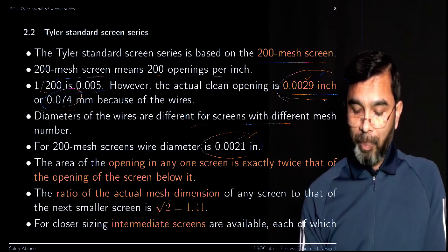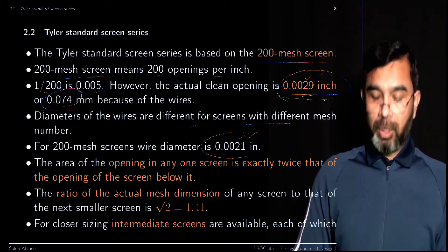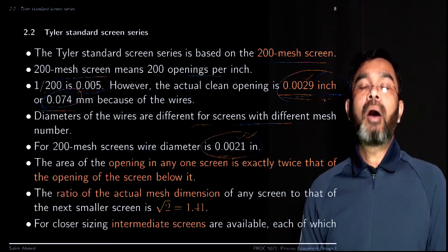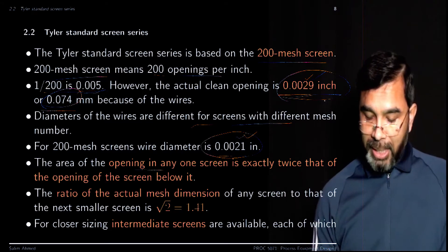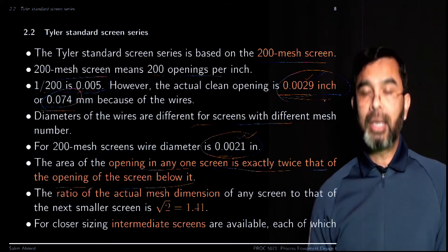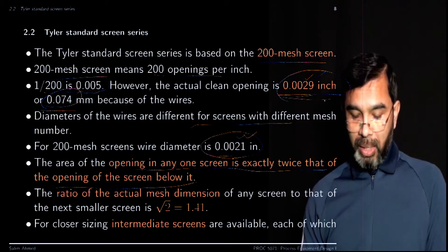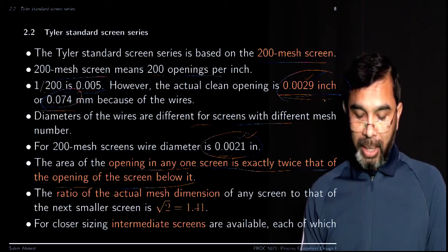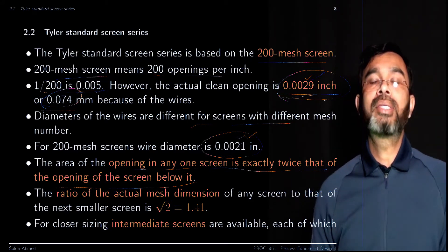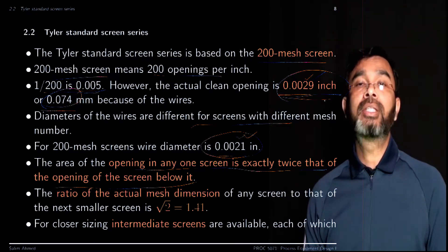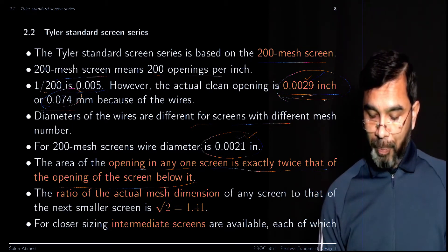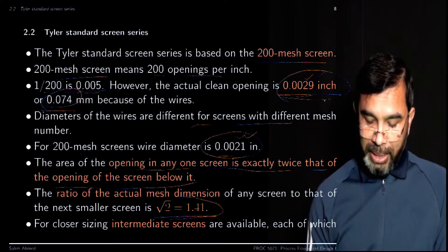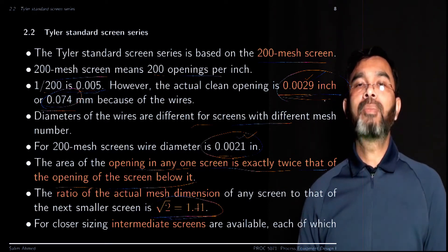Adding the opening (0.0029 inch) plus the wire diameter (0.0021 inch) gives 0.005 inch, which is 1/200. The other screens are defined such that the opening of any screen is exactly twice the area of the screen below it. Since the area needs to be twice as large, the opening size will be the square root of 2, which is 1.41. So the screen above the 200 mesh has an opening 1.41 times 0.0029 inch.